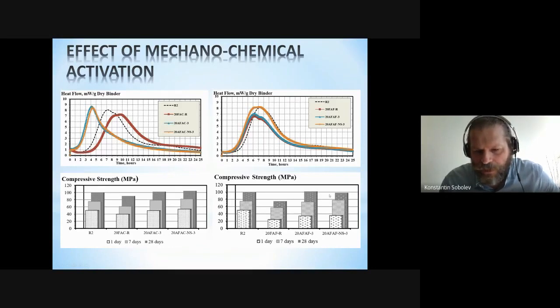And if you look at activated class F material, obviously activation versus reference class F really improved the response, but not the first day response. The 7 and 28 days response was really very similar to that of reference Portland cement. So class F material didn't form any nanostructures, so it was just again 3 hours of milling, and it was still useful, but not really at these early stages of hydration.